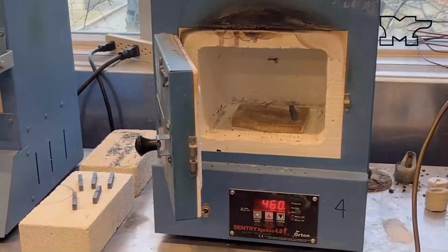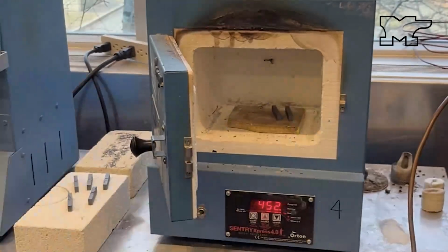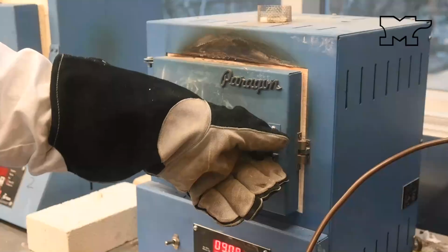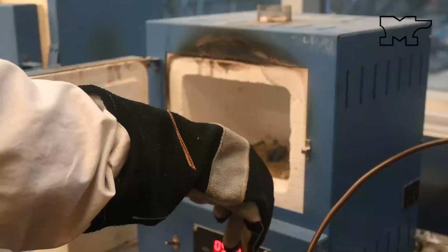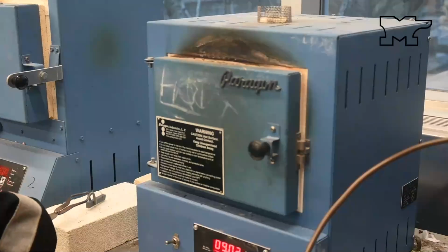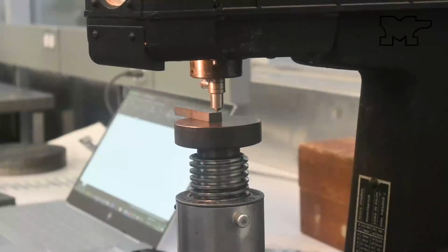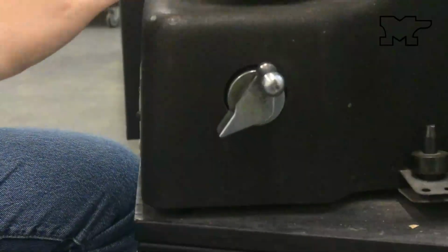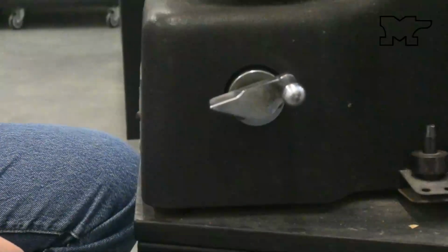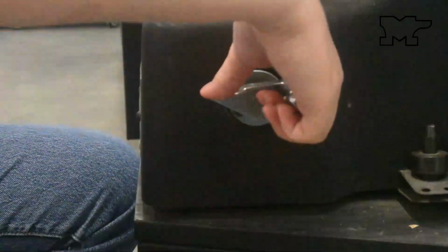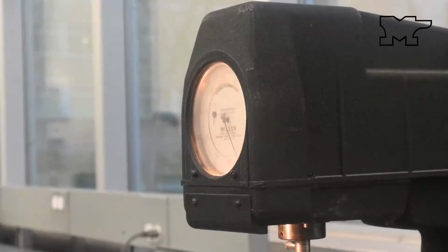All of our samples were cut on a wire EDM at the McMaster machine shop. They were then solutionized and aged for various times to maximize fracture toughness while maintaining a minimum hardness of 54 HRC. For the first step of our mechanical testing, we measured hardness using an analog hardness tester and discovered that even at short times, our minimum hardness was hit, resulting in us shortening our aging times.